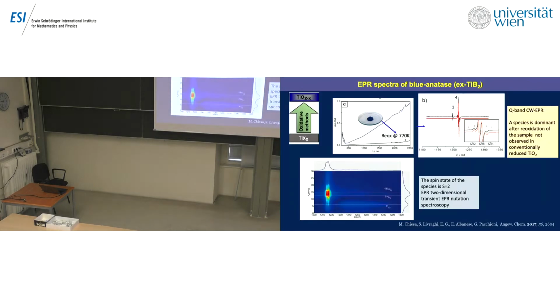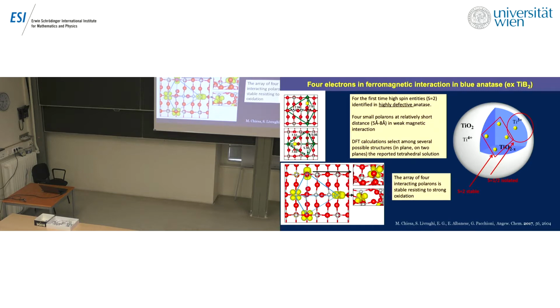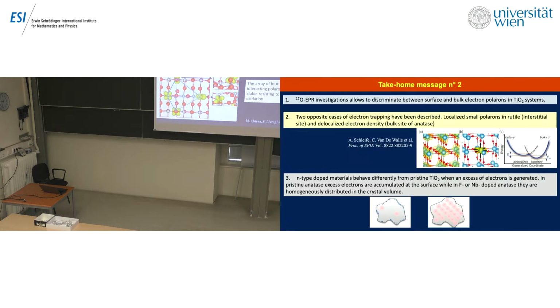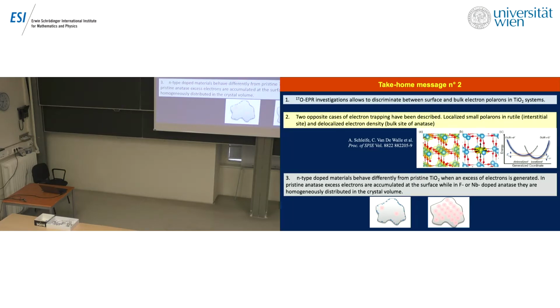I skipped the last two things related to states of interaction of polarons, magnetic interaction of polarons creating high spin states, which is less important today. And so the second take-home message: oxygen-17 investigation allows us to discriminate between surface and bulk. Two opposite cases of electron trapping have been described: localized Ti3+ polaron in rutile, and delocalized electron density at bulk sites of anatase. So in this case, we have both, okay?